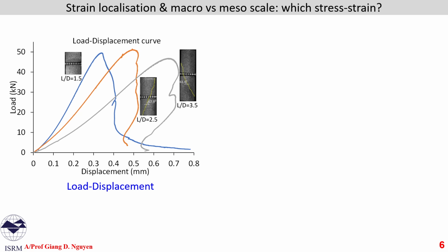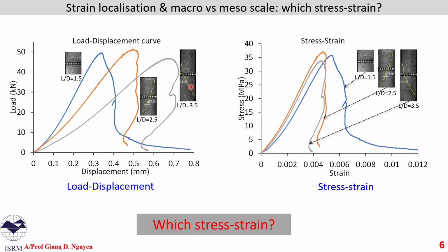Now, if we test three different aspect ratios, length by diameter, 1.5, 2.5, and 3.5, and plot the load displacement curve, we get these three curves, very distinct, and the longer the specimen, the softer the behavior. Softer means the initial elastic stiffness is lower, and the post peaks are also very different.